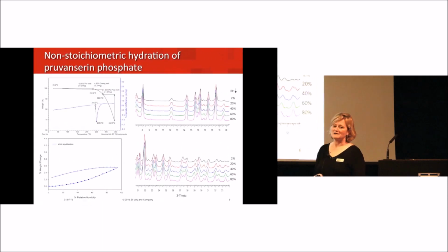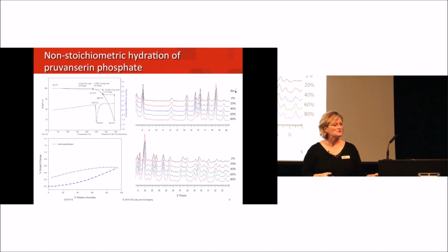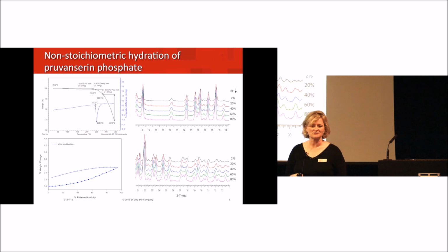That example showed how the CSD was important based on what you should see in the crystal structure, and I thought as a complement to that, maybe I could talk about what you don't see in a crystal structure. So this compound was under development once again a number of years ago, pruvanserin. It was being developed as a phosphate salt, and it was characterized as a hygroscopic anhydrate. We had thermal analysis data which showed about 1% weight loss when we heated this material.